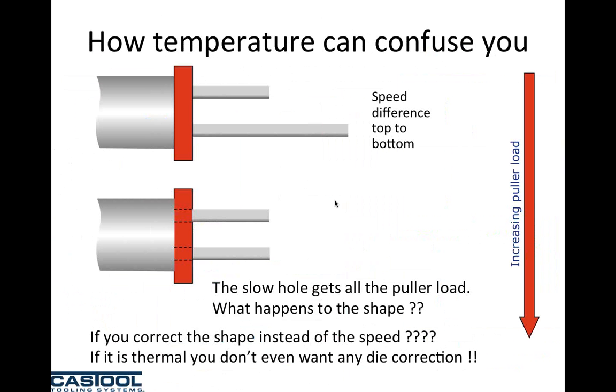And again, temperature affects flow rates. Whether it's the container affecting the die or the die slide affecting the die, even if you use chest ovens, they tend to heat the die from the bottom up. So when you bring a die out of the chest oven, typically the bottom of the die will be hotter than the top of the die. If you leave the die in the die slide for 5 minutes, the bottom of the die will be colder than the top of the die.